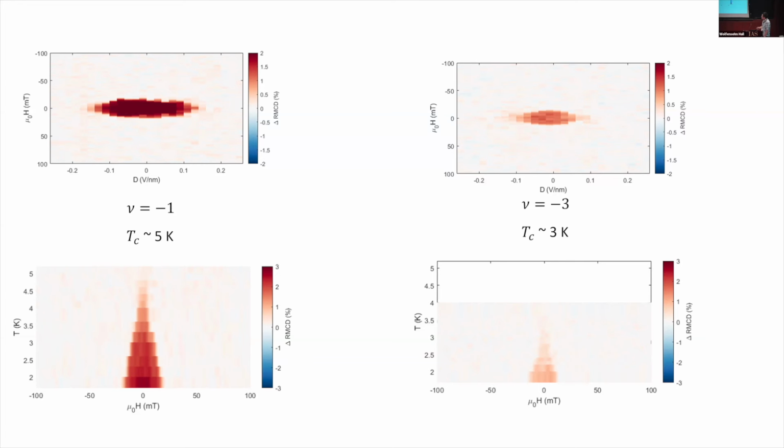Let me comment on the Curie temperature a little bit. If you remember, I showed you that the Curie temperature for the 3.74 degree sample is about 14 kelvins for filling factor -1, and for 2.6 degrees, the Curie temperature is about 9 to 10 kelvins. Now for 2.1 degrees, at filling factor -1, the Curie temperature keeps dropping to 5 kelvins. So everything is consistent, because the magnetism comes from direct Coulomb exchange.